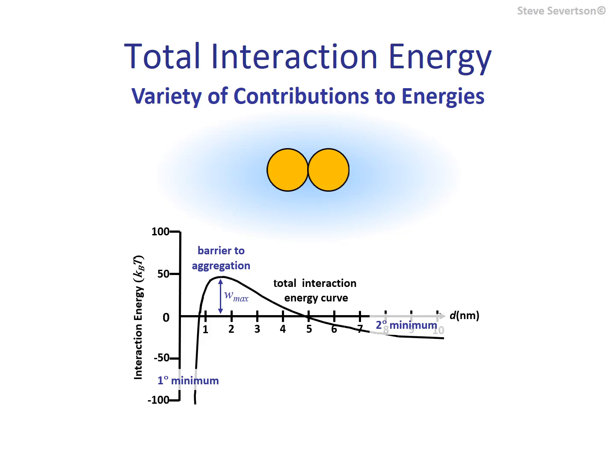Thus, the conceptual model provided here is quite useful in explaining changes in stability based on modifications to particle interactions. For example, adding a non-ionic surfactant to an electrostatically stabilized hydrophobic colloid will likely increase the repulsive energy and thus increase the energy barrier to aggregation, slowing it down and providing increased stability to the hydrophobic colloid.